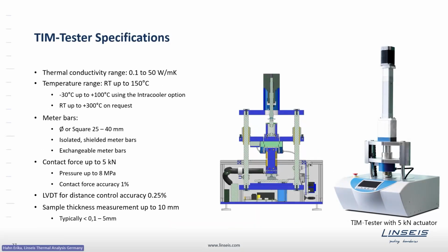The main unit is designed for thermal conductivities between 0.1 and 50 watt per meter Kelvin, and as most of the materials the TIM tester is able to determine are used in electronics, the temperature range of room temperature up to 150 degrees Celsius is realized in the basic unit. With some modifications, one can also reach sub-ambient temperatures going down to minus 30 degrees Celsius. Also, we have a high temperature model going up to 300 degrees Celsius.